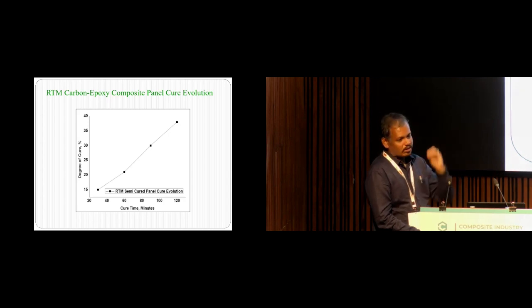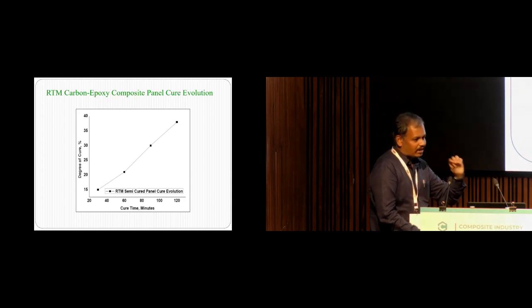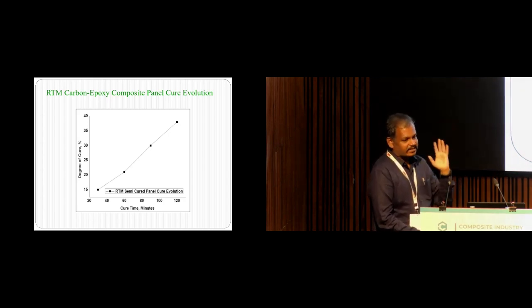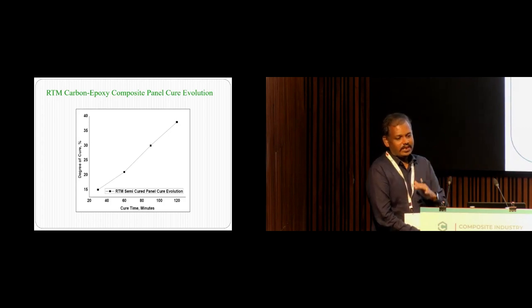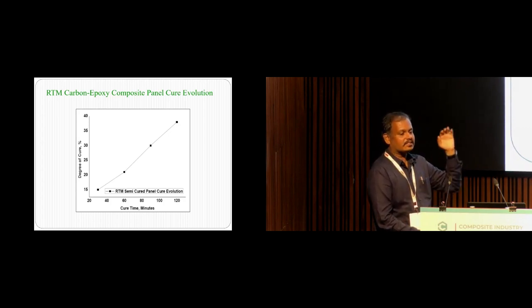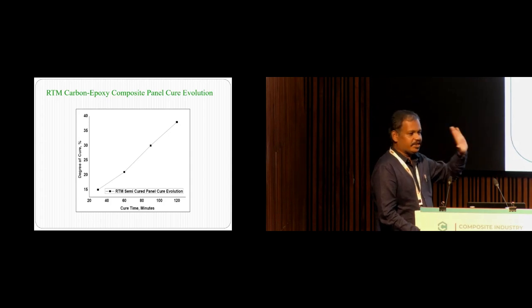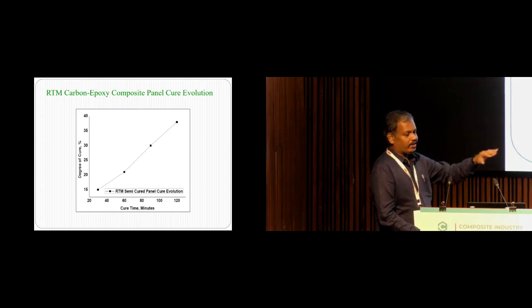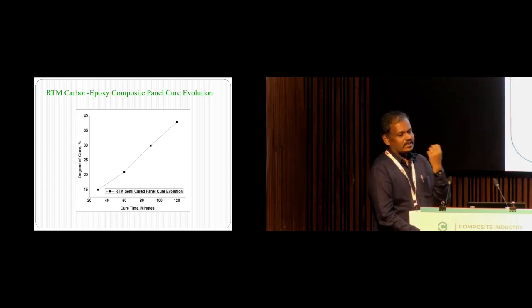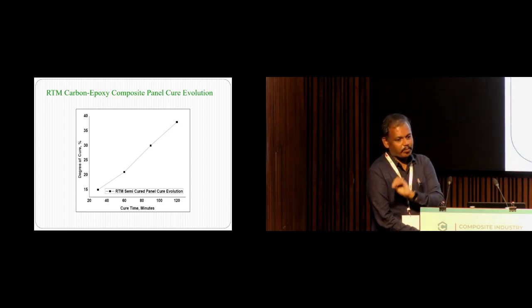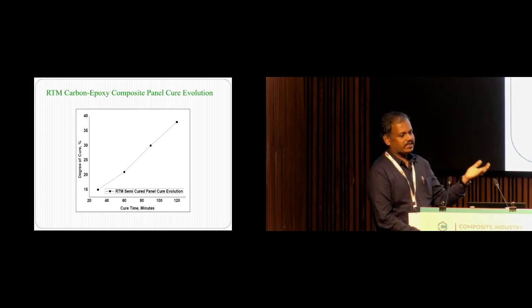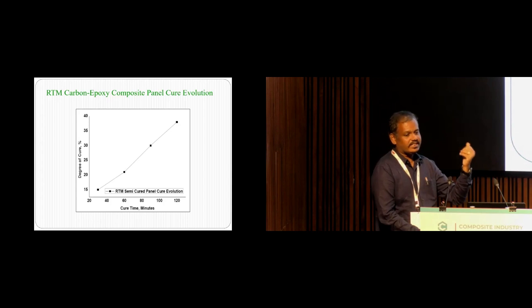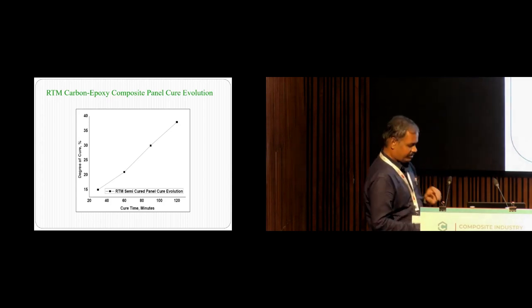So we have found the model. It will tell you by how many degrees the temperature has to be increased. Say, for example, if I am applying 150 degrees centigrade for 30 minutes for the resin curing, what cure cycle has to be applied to the composite panel such that you get the ideal curing? Say 30% ideal curing will happen with the resin as well as with the composite laminate.